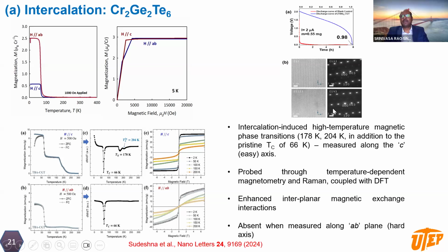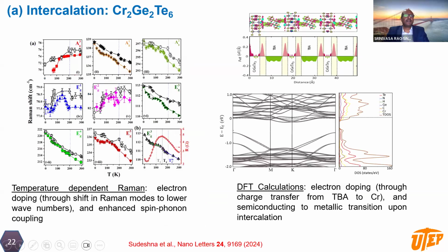And our collaborators at Argonne National Lab did STEM imaging on the pristine as well as the intercalated crystal, and they measured that along the c-axis the layer gap increased, whereas along the ab-axis everything is the same as in the pristine case. That is an indication that the gap increased, meaning the layers were intercalated with TBA+. And our collaborators at NIST conducted temperature-dependent Raman, extrapolated the spin-lattice coupling, and found a strong electron donating effect from TBA+. These experimental findings were supported by DFT calculations, showing electron doping, a charge transfer from TBA to chromium in this case. And that led to the semiconducting to metallic transition, particularly the one we saw at 204 Kelvin.